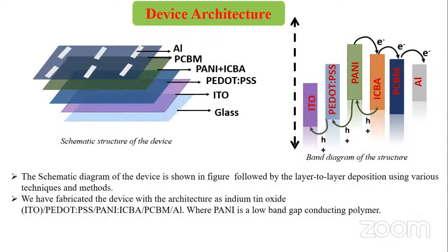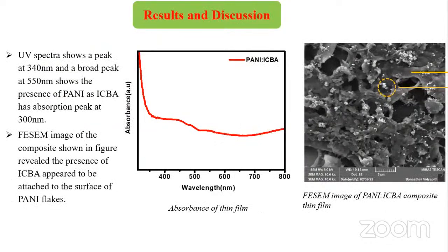Next is the device structure. Firstly, the ITO coated glass substrate we have used. Then PEDOT:PSS is spin coated for HTL. After that, PANI and ICBA used as the active layer. After that, PCBM used as ETL, and the aluminum electrode deposition is done by the thermal evaporation unit. And the energy band diagram is clearly shown here for the transportation of electron as well as the hole. And next is the result and discussion.